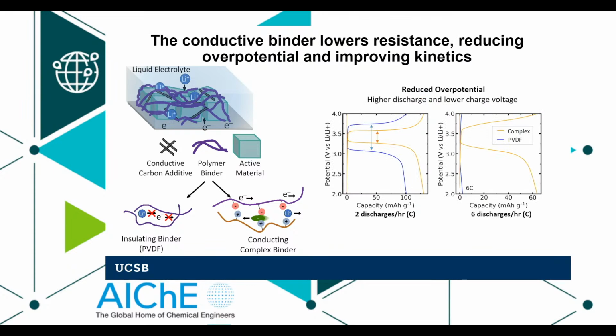But perhaps more importantly, this is again, blue is the PVDF polymer, orange is the complex, and this is potential versus capacity. We're running at much lower overpotentials in these systems. And what that's saying is because we have less resistance in the system overall, we don't have to charge it up quite as much. And by not having to charge it up as much, we're running a much lower risk of having adverse side reactions and parasitic reactions happening that would destroy the system overall.